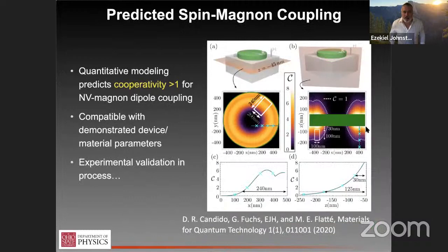And here I'm referencing a theory paper that we recently put out in collaboration with the Flatté group. Really the Flatté group put it out, and we contributed along with the Fuchs group at Cornell. And what we're looking at here in this schematic, the green is a disk of VTCNE. And so this is essentially a magnon resonator deposited on the surface of diamond. And then what they've done is assume some distribution of NV centers in the diamond, and then take line cuts as a function of depth or across at a fixed depth across the disk. Sorry, my pointer was backwards when I was saying that.